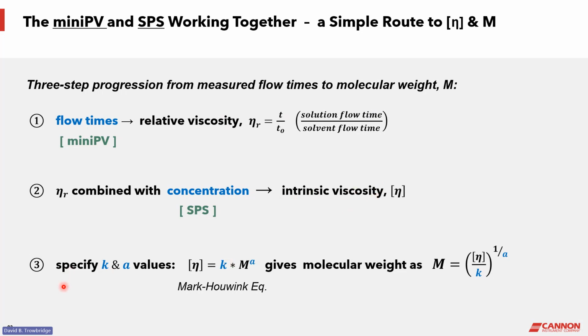And then we combine the measured intrinsic viscosity with selected K and a values and incorporate those into the Mark-Houwink equation and use the form that allows us to calculate molecular weight. So this is the procedure that we follow and the important role that the mini PV and the SPS contribute.